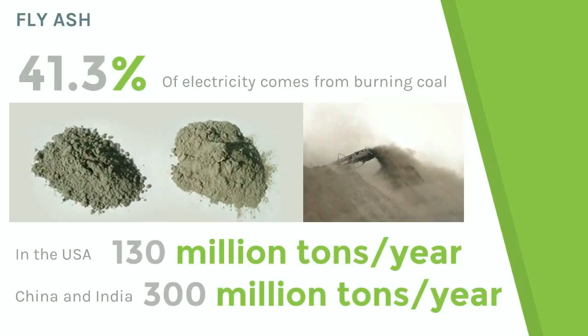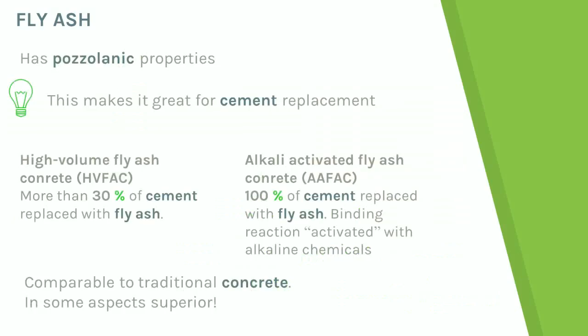In Serbia alone, just one of our 6 power plants produces 100 tons of fly ash every hour, and 24 hours a day, 365 days a year. In fact, in Serbia, about 200 million tons of fly ash are currently deposited at a surface area of 1,500 hectares. Fly ash, as well as a number of other industrial byproducts, consists mainly of silicon and aluminum oxides, and has so-called pozzolanic properties, which means it reacts with cement hydration products and enforces the paste matrix, contributing significantly to the properties of the final material.